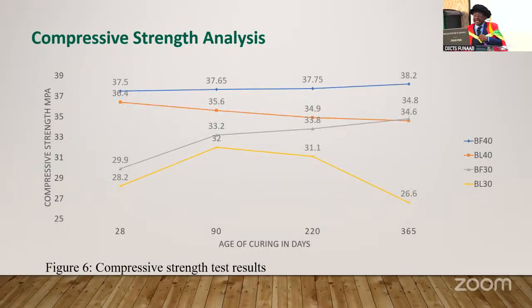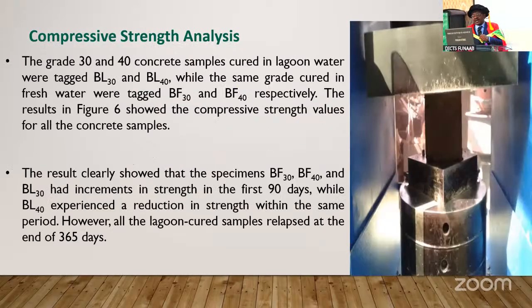The grade 30 and grade 40 concrete samples were cured in lagoon water and fresh water. The ones in lagoon water were labelled BL30 and BL40, while the ones cured in fresh water were labelled BF30 and BF40 respectively. The result in figure 6 shows the compressive strength values for all these concrete samples over a period of 1 year. The result clearly showed that the specimens BF30, BF40, and BL30 had an increment in strength in the first 90 days, while BL40 experienced a reduction in strength within the same period. However, all the lagoon cured samples relapsed at the end of 365 days.